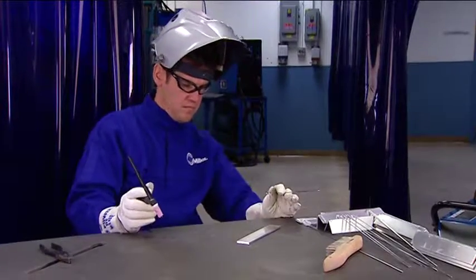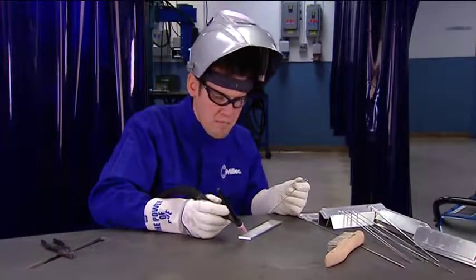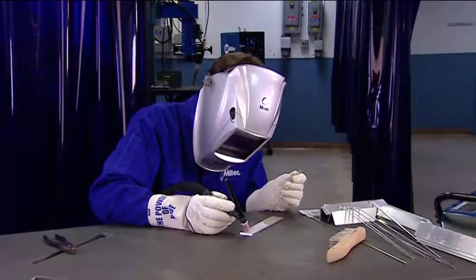Once you begin welding, you'll need to look for a few indications that you have the proper setting. When you strike an arc, look at the surface appearance of the puddle. It should be shiny and clean without a heavy film or any particles floating on the surface. If you see dark spots in the puddle, adjust the AC balance down because you need a little more cleaning action. If the puddle appears shiny and clean, but you have a wide etching zone around the weld, turn your balance up because you have too much cleaning action.